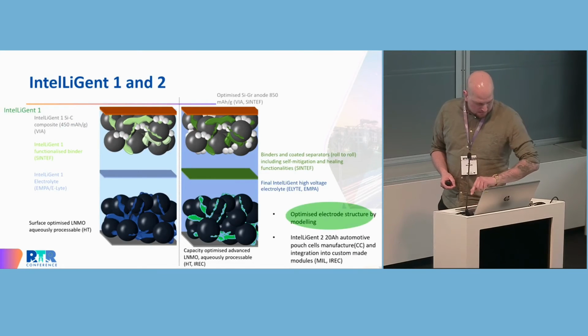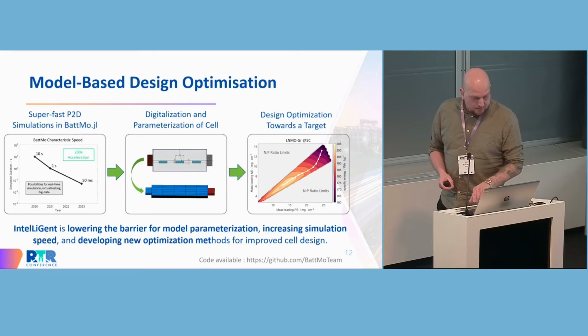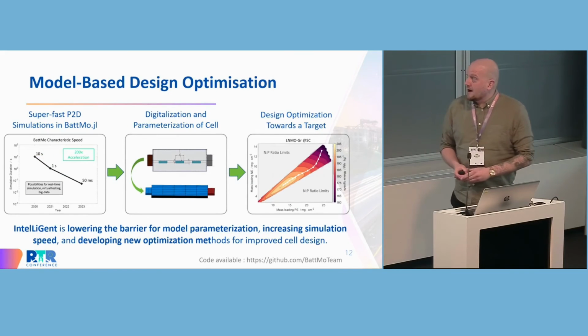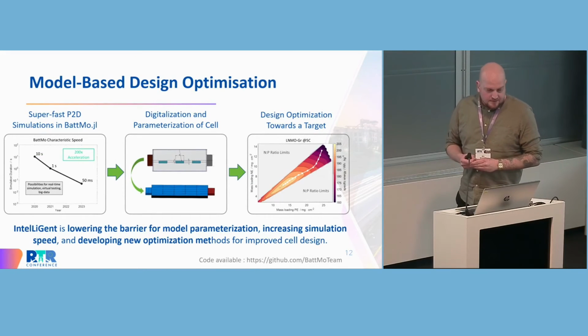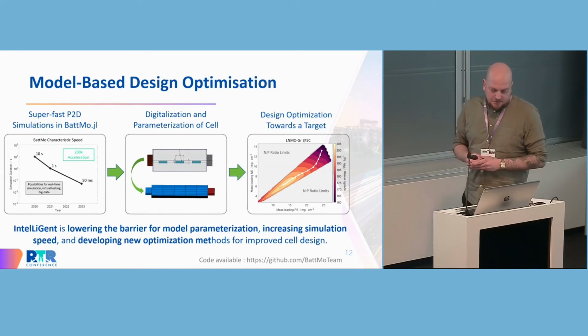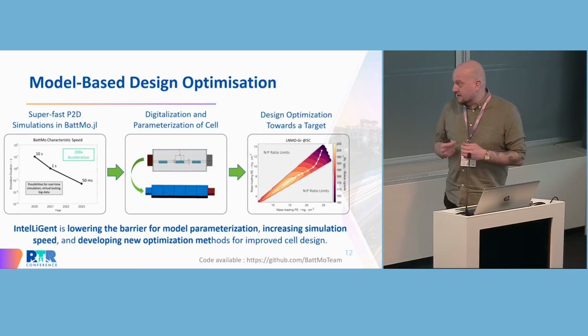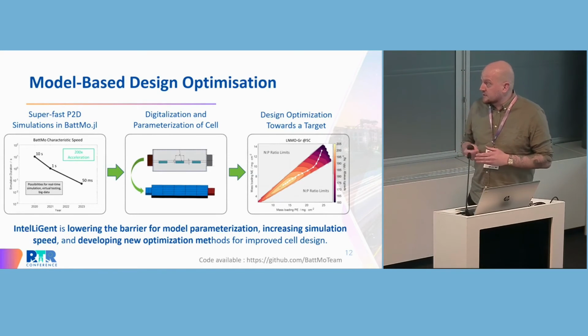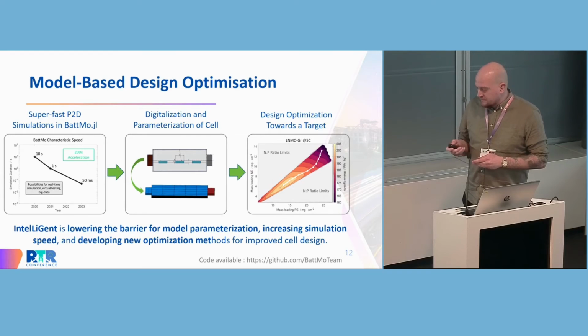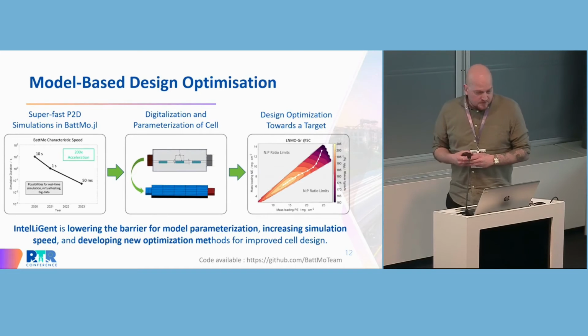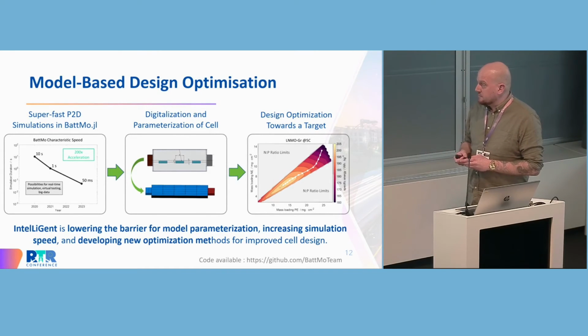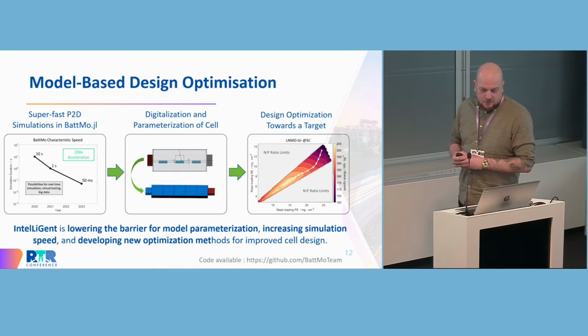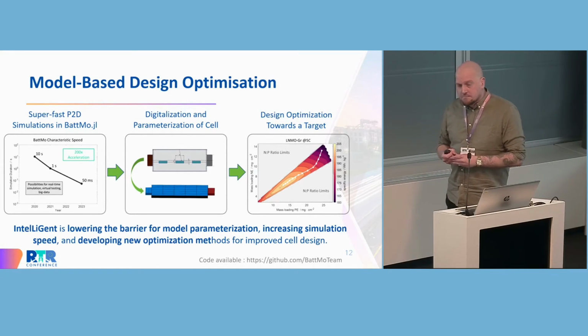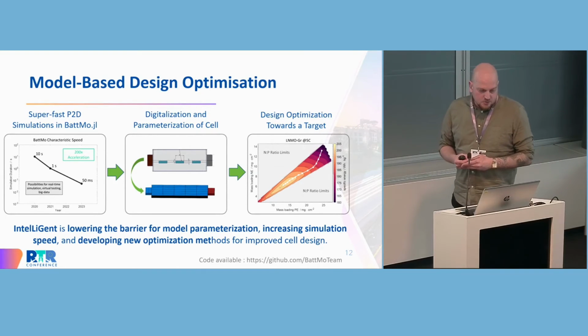As a last point, I'm not sure how I'm doing for time, I would like to briefly mention, 3 minutes, that's perfect, our modeling activities. So Intelligent is heavily based on model-based design optimization, and I'm sorry, I'm really not the best presenter for this, but we're trying to lower the barrier for model parameterization and increase simulation speed drastically. So on the very left, we see a battery simulation platform that was developed within SINTEF, BATMO. And in the last 3 years, we managed to lower the time for P2D simulation down to 50 milliseconds. So we can really lower the burden that people say that these physics-based simulations are too time intensive.